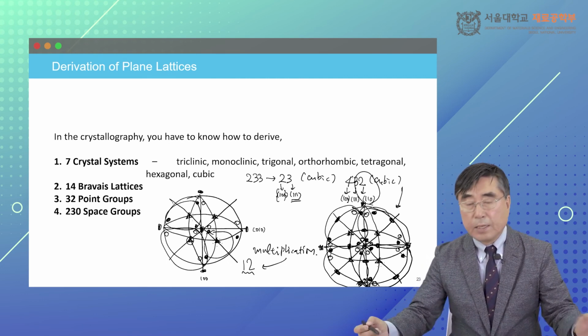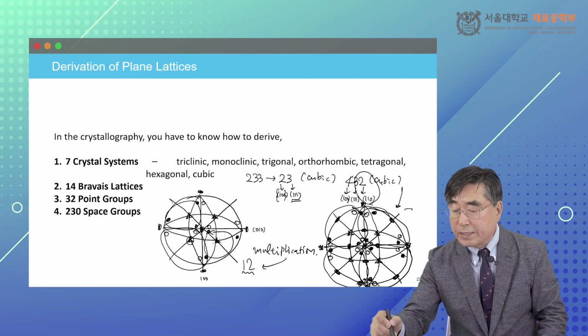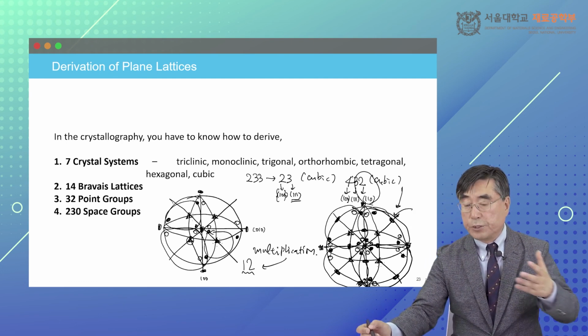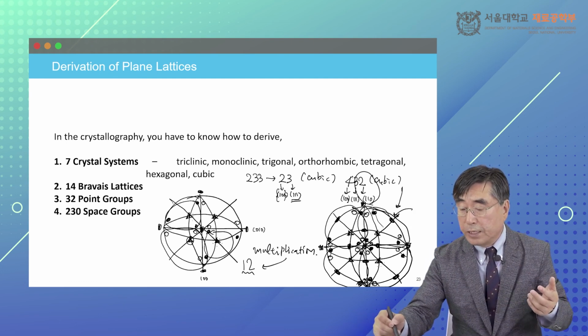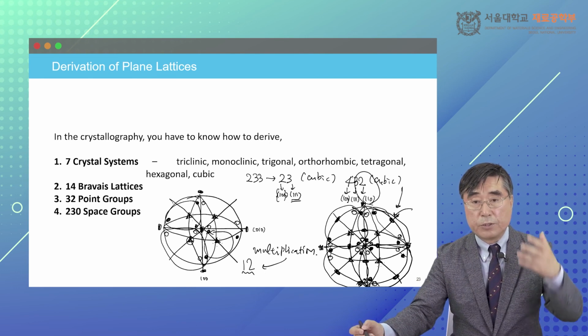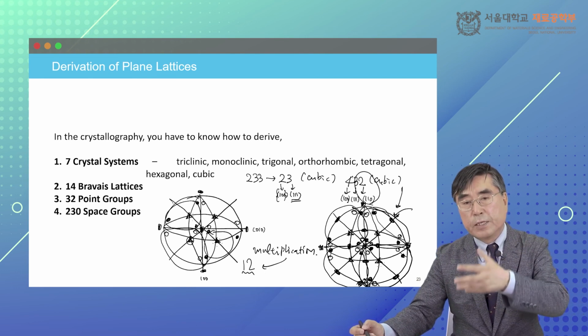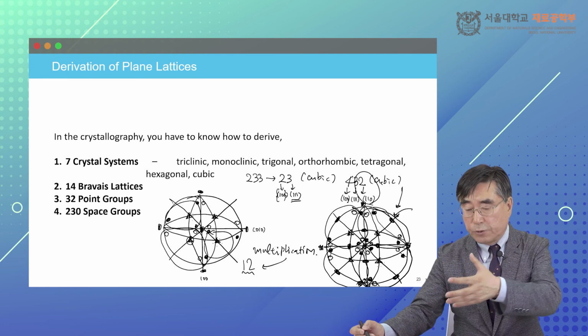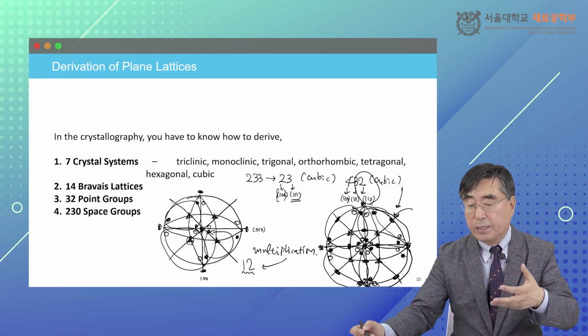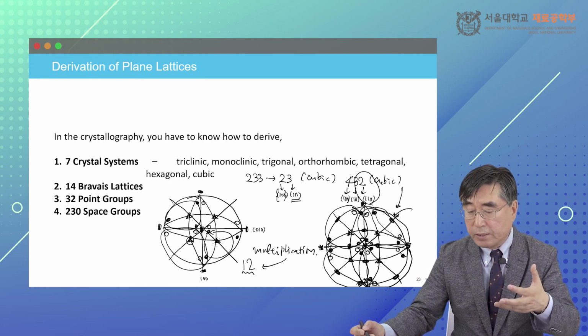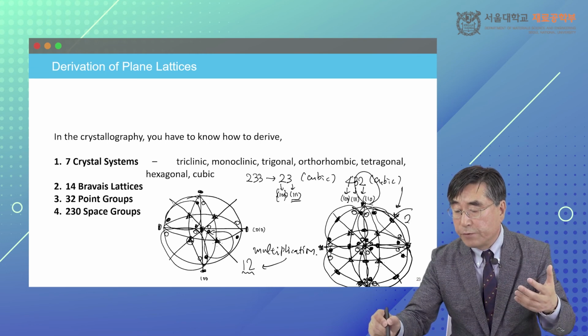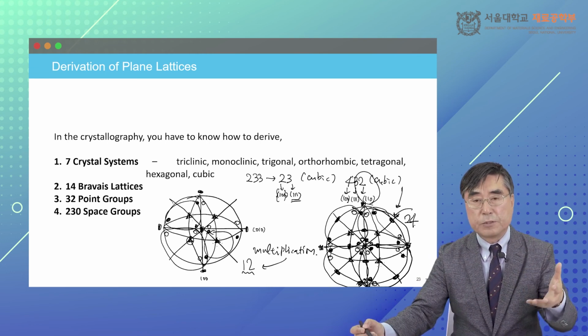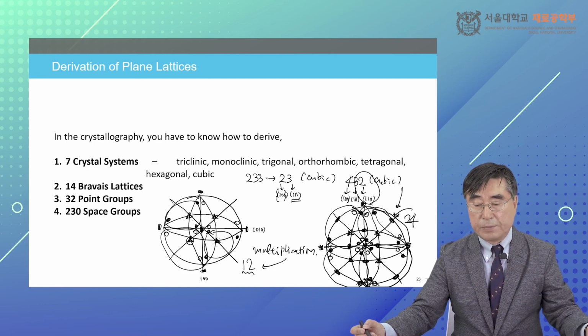Okay. Now you don't have to do this set of twofold symmetry operations. If you do it, you know that it's already in there. So the multiple rotation operations have been done so far. Now you see how many poles are generated. There is a 24 multiplication. It generates 24 poles by these symmetry elements.